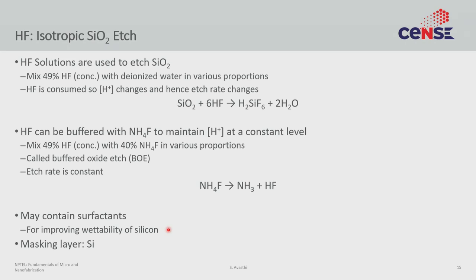Typically we use concentrated HF with around 40% ammonium fluoride — in various proportions, usually diluted. This composition is what is called Buffered Oxide Etch, or BOE. For all BOE solutions, the etching rate tends to be uniform even for long etchings. BOE also contains surfactants, which help reduce the loading effect and reduce surface tension so the liquid can penetrate small holes. Often, the specific surfactants are a trade secret from the vendor, but if you get an etching solution from a reliable semiconductor vendor, you trust that the chemistry will work. The masking layer for HF when etching silicon dioxide is silicon itself — HF etches silicon dioxide well but does not etch silicon, giving nearly infinite selectivity.